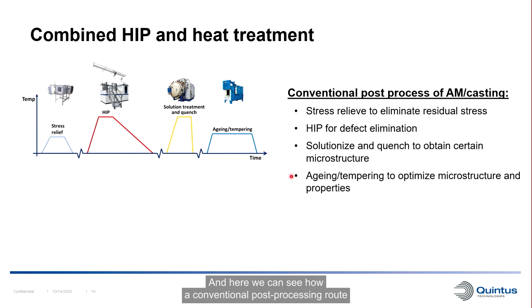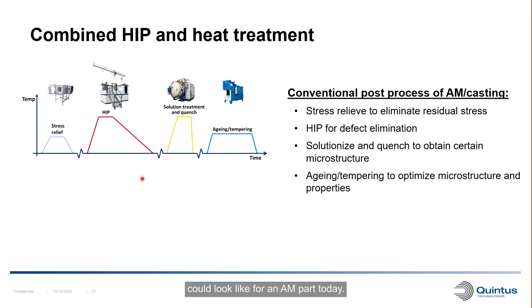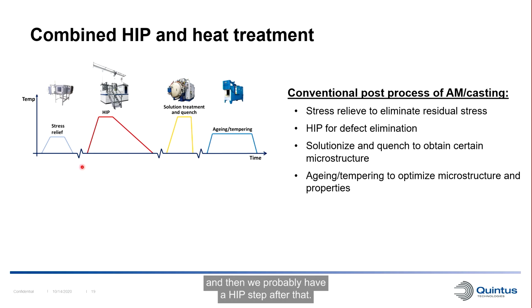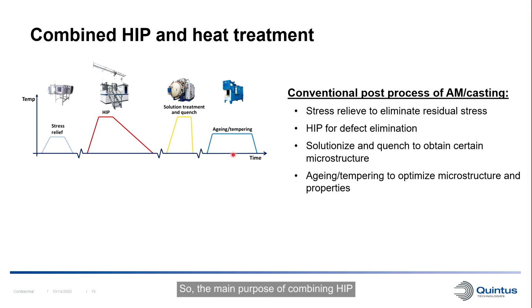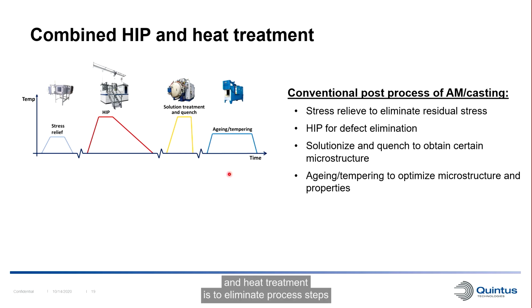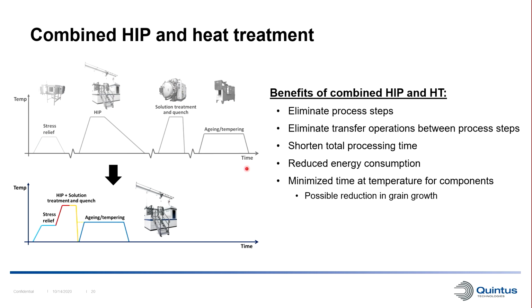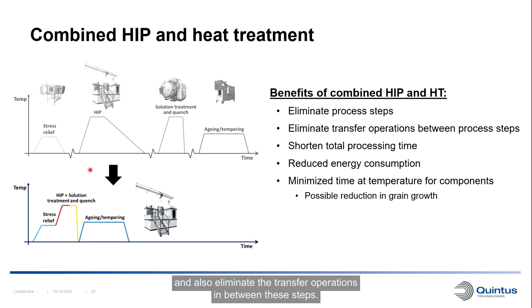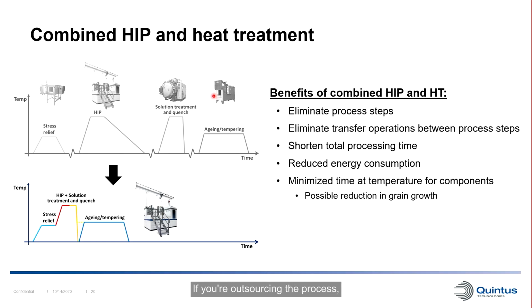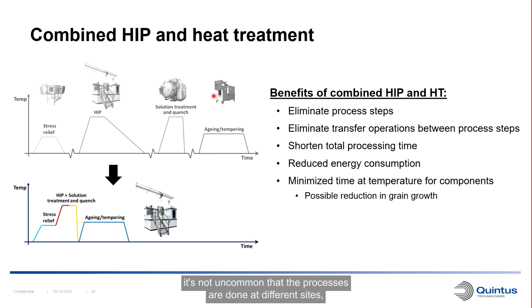And here we can see how a conventional post-processing route could look for an AM part today. We might have a stress relief step, and then probably a HIP step after that. Then we could have a solutionize and quenching or cooling step, and then probably an aging or tempering step after that. So the main purpose of combining HIP and heat treatment is to eliminate process steps and also eliminate the transfer operations in between these steps. All these steps are typically done in different equipment. If you're outsourcing the process, it's not uncommon that the processes are done at different sites or at different suppliers. So the main purpose is to combine these steps into one cycle performed in the HIP.